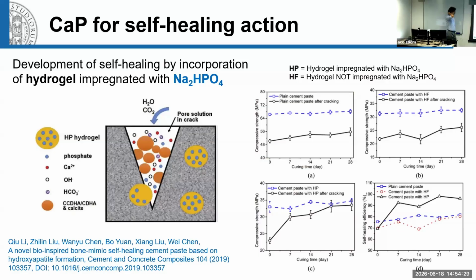A different strategy is based on the phosphate technology that I presented. So the idea is to incorporate in the cement, in the concrete, some hydrogel containing a phosphate precursor. In this case, again, it's sodium phosphate. When a crack develops in the concrete, then the phosphate precursor is released from the hydrogel. It's able to react with calcium ions that are present in the pore solution, with the water that is present in the environment and comes in from the crack. And in this way there's formation of a calcium phosphate and there's healing of the crack.